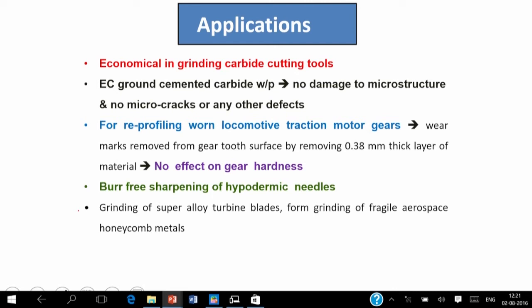So these are the applications of the electrochemical grinding operation. It is used for grinding of carbide cutting tools, and it is economical for this. When electrochemical grinding cemented carbide workpieces, there is no damage to the microstructure, no micro cracks or any other defects. It is used for reprofiling locomotive traction gears, where wear marks are removed from the gear tooth surface by removing a 0.38 millimeter thick layer of material. The machining process does not affect the gear hardness.